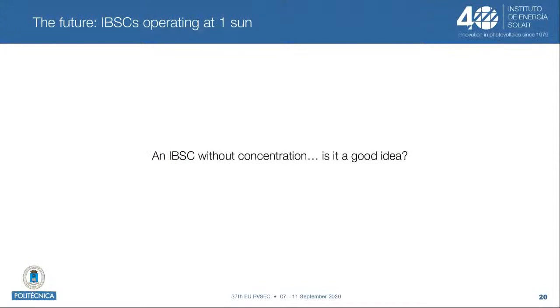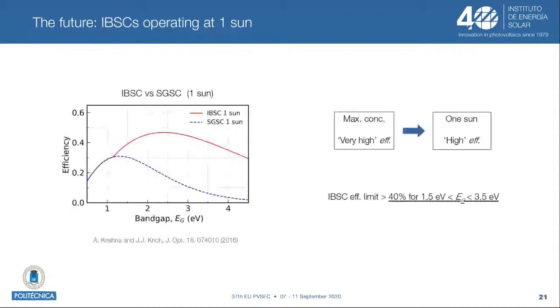So the first question that comes to mind now is: is it still a good idea to use an intermediate band solar cell without concentration, so at one sun? The answer, we think, is yes. To support that, I show here the plot of the efficiency against the band gap, as I did at the beginning of the presentation for high concentration. This is for one sun. And you can see that the intermediate band solar cell achieves efficiencies well over 40%, still at one sun. And it does so for a very broad range of band gaps between 1.5 and 3.5 electron volts. So we think there is a vast variety of materials that can be explored as an absorber for an IBSC working at one sun.